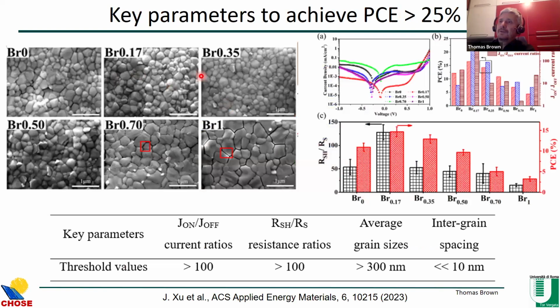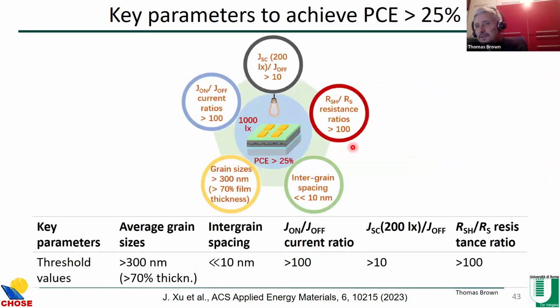So we carried out SEM microscopy and looked at the grain sizes and also at the separation between the grains for these films. We looked at the recombination currents versus the forward currents, and also the shunt resistance over the series resistance. And to summarize, we found that to achieve high efficiency perovskite devices, you needed an average grain size higher than 300 nanometers. So more than 70% of the film thickness. This will allow the photo-generated carriers to be collected at the electrodes without finding many grain boundaries where recombination takes place.